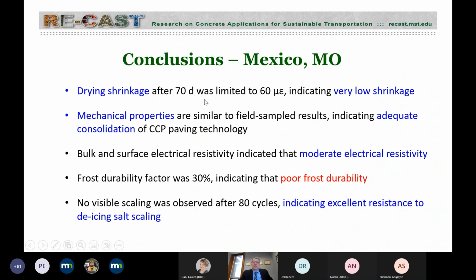We also measured shrinkage. I did not show the results, but the drying shrinkage was very, very low. After 70 days, 60 microstrain, which is very, very low shrinkage. Mechanical properties, we found out that they are similar to those of field samples, indicating that this RCC mixture had adequate consolidation. We saw some weak signs of consolidation in some of the samples. I mentioned that in the flexure sample, where the flexure strength was much lower than the companion samples taken nearby. The frost durability was very low, 30% residual strength, and the de-icing salt resistance was very high, as we saw before.